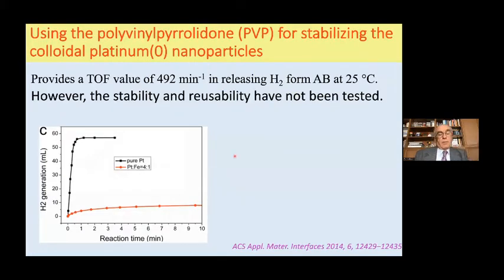So how can we make the nanoparticles stabilized? There are a few ways. One of them is by adding the stabilizing ligands into the solution. And the stabilization will depend on the nature and the concentration of that stabilizing agent. In this study, polyvinylpyrrolidone has been used as stabilizer, and nanoparticles are obtained quite stable. We don't know actually how stable they are. They have never tested, but